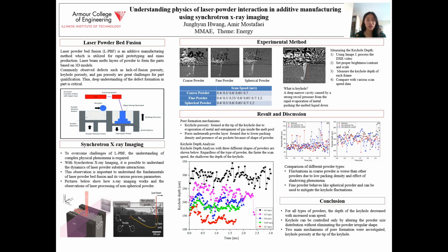To overcome these challenges, synchrotron X-ray imaging can make it possible to observe the dynamic of laser powder substrate interactions and also understand the fundamentals of laser powder bed fusion and its various process parameters. Like in the pictures below, metallic powders are set between two glassy carbon plates while the laser beam goes through the powder. An X-ray beam penetrates the plates and powders to generate the X-ray imaging of the laser powder bed fusion process.